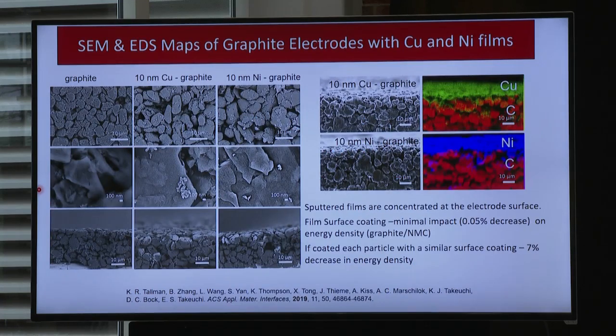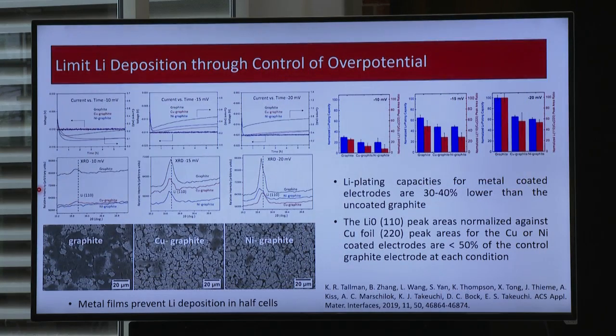So what we did then was deposit very thin films of either copper or nickel on the surface of the graphite electrodes, with the idea that in this case, we're maximizing the overpotential for lithium deposition and minimizing the overpotential for lithium insertion into graphite, so that we might be able to offset some of the lithium deposition.